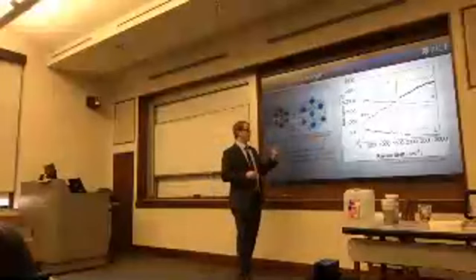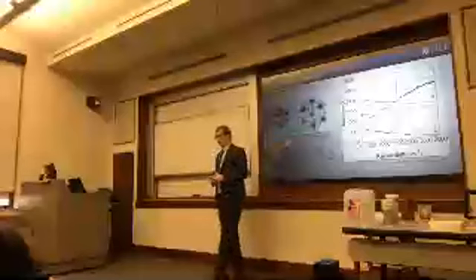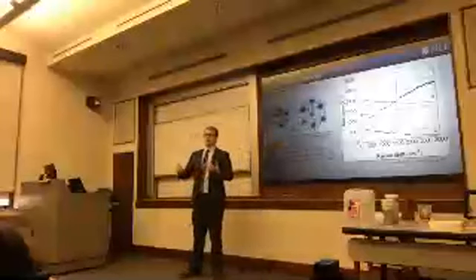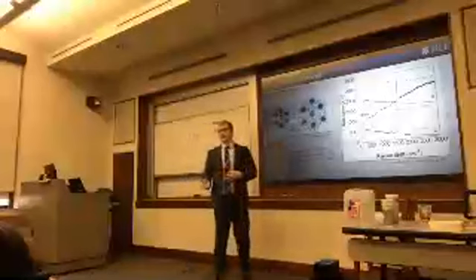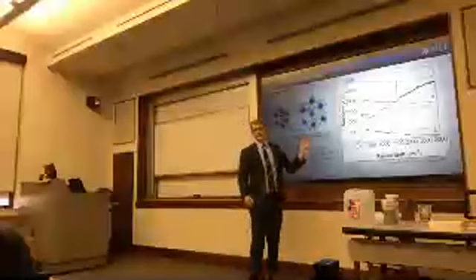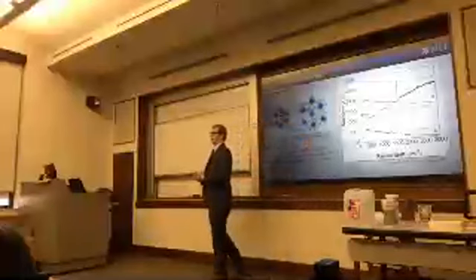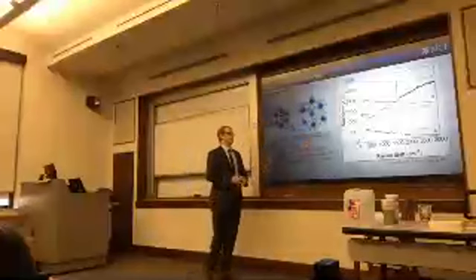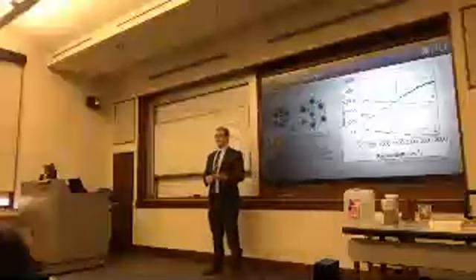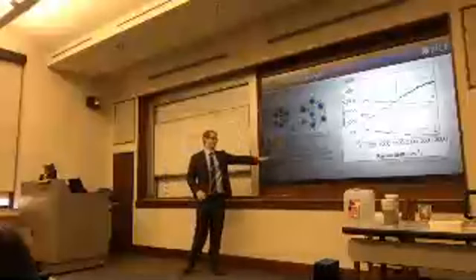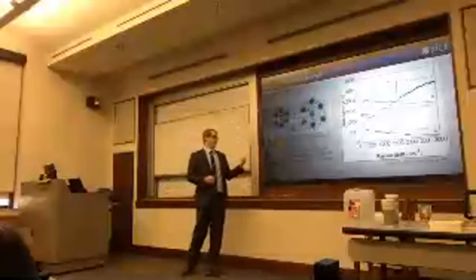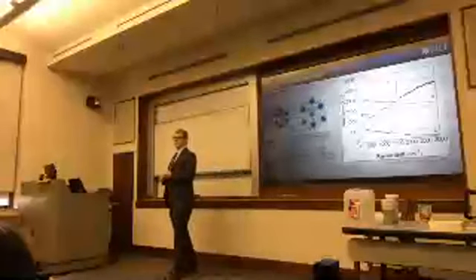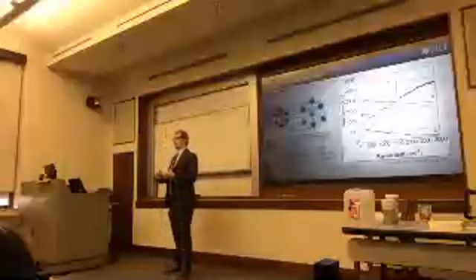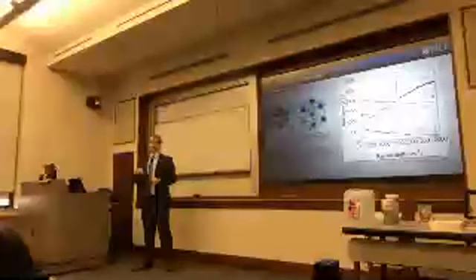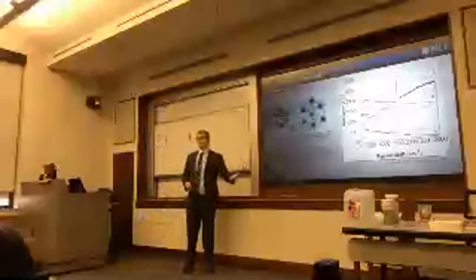Now, if you take the nanotubes in the acid, you don't get a G peak. The reason for this is because the electrons that you're probing with that laser have been depleted by the acid and now are no longer available for excitation. However, if you use a higher energy laser, such as 514 nanometers, you probe higher energetic electronic transitions, and now you recover this G peak. What's interesting is that the position of that G peak has shifted by 23 wave numbers. So we'll refer to the shift going forward as a DG. This increase in G peak shift is a direct measure of the increase in the carbon-carbon bond stiffness, which is, again, a way for us to quantify the strength of the interaction between the acid solvent and the nanotube. So a stronger interaction will result in a higher shift.